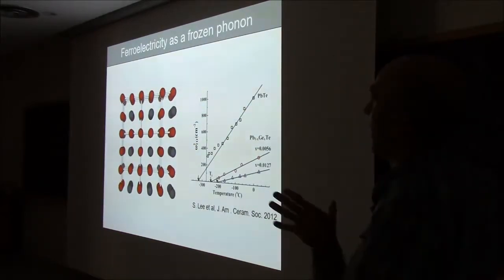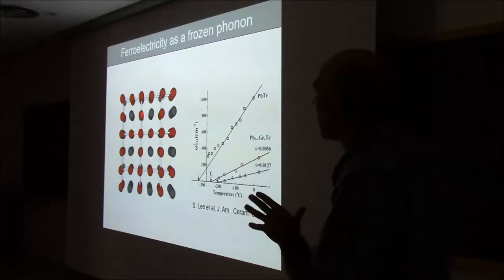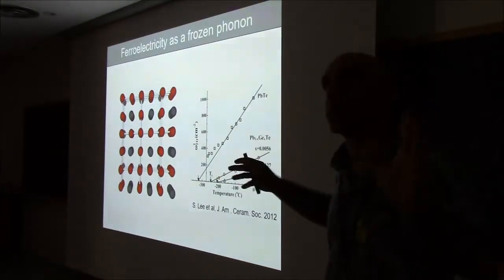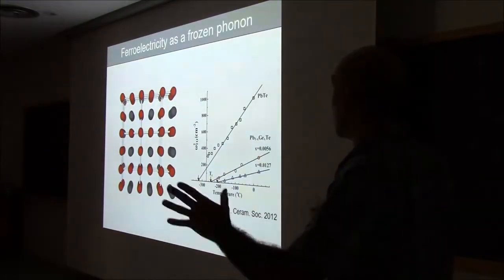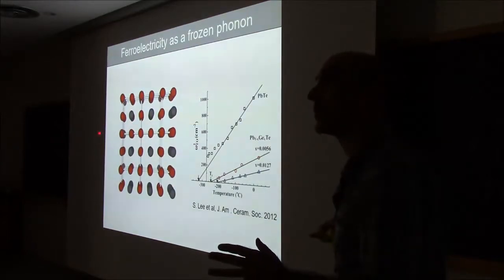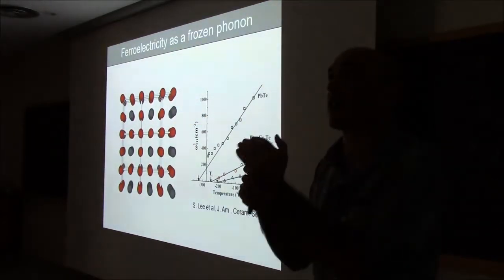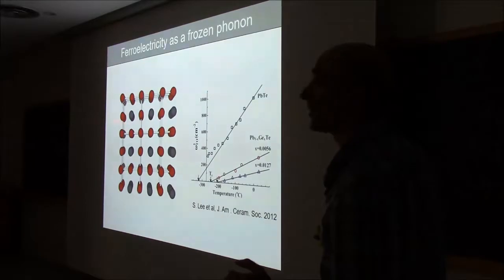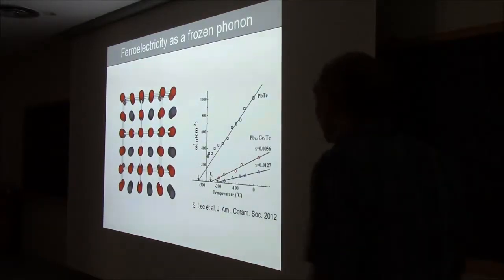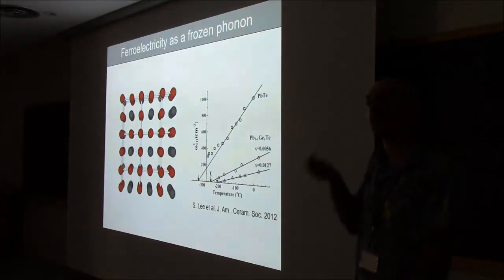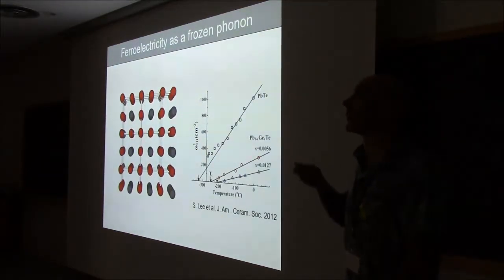Okay. At high temperatures, as long as this is vibrating around the center, this is centrosymmetric. As you cool things down, this phonon gets slower and slower and slower, and eventually it freezes. And when it freezes, it freezes in a polar position. Okay. And this actually is a good trick to try and identify ferroelectricity in materials that are normally very conducting.